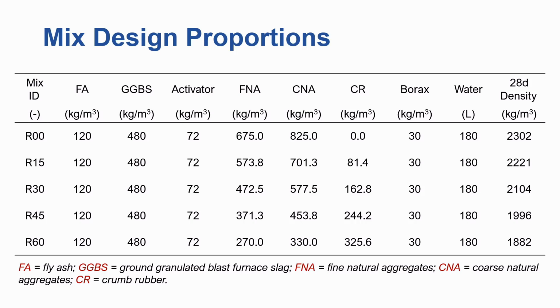We named them R0, R15, R30 up to R60, and this just refers to the rubber replacement ratio. So R0 had no rubber content, and then R15 is we replaced 15% of the natural aggregates with rubber particles, and so on until R60, which had the largest rubber replacement ratio of about 60% of the natural aggregates.